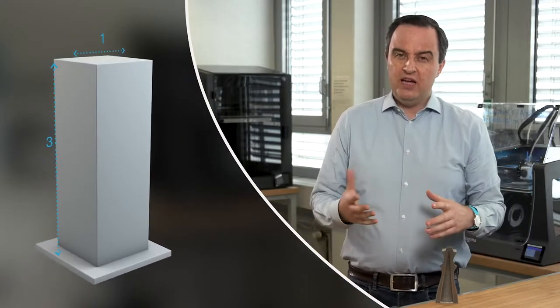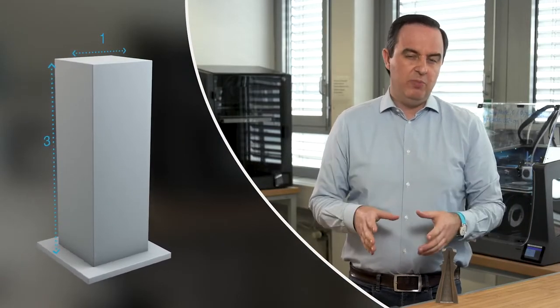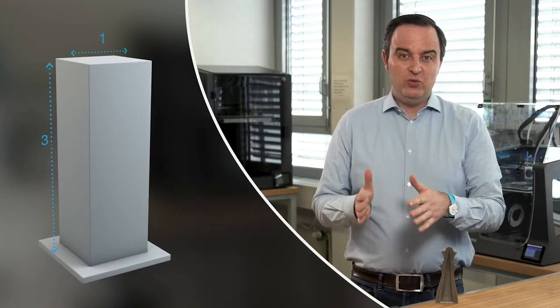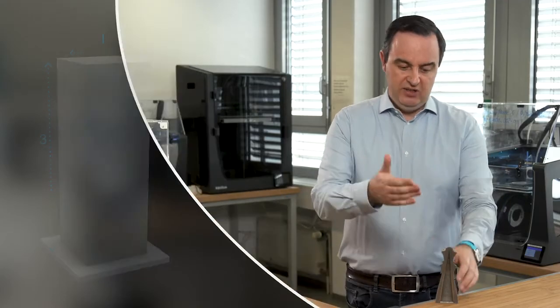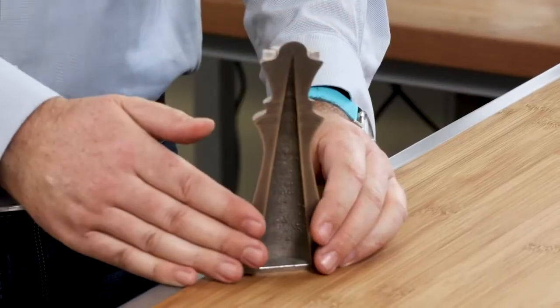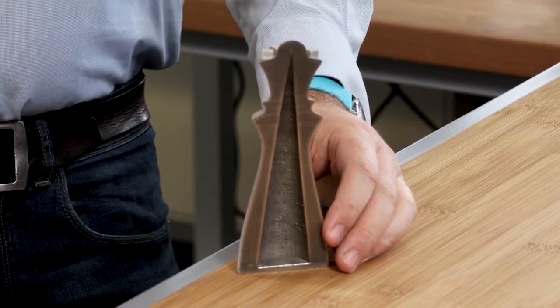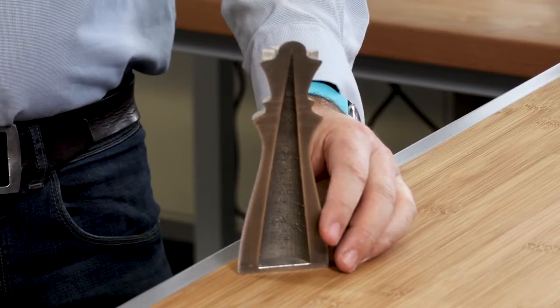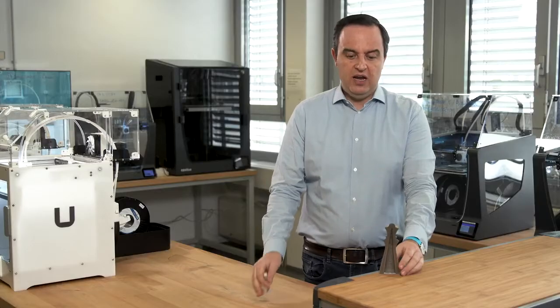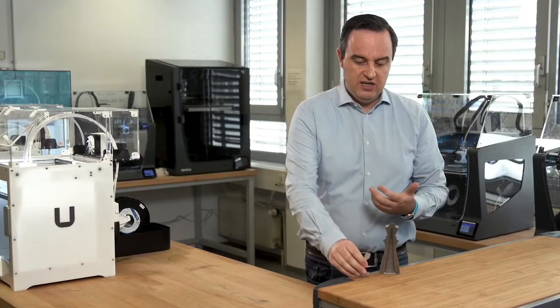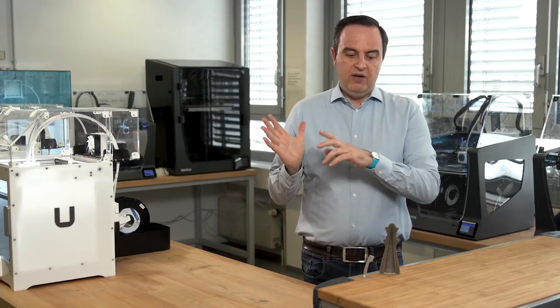And you can see, why do we ask about that? The taller and thinner part we're going to get can tend toward distortion or leaning, as we did in the King here. This has been cut in half. And you can see in this version, it started to tilt slightly over to the side, and you'll start to get distortion. And other parts like this, we can see again where you have too much mass on the top and not enough thickness on the body of the part, it'll begin to lean down through the viscosity of the material during the sintering temperature.